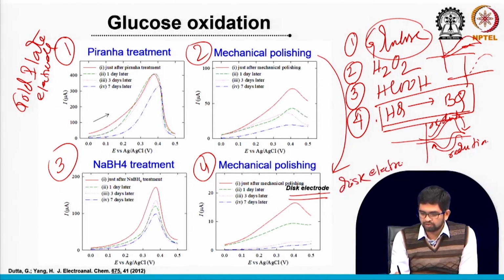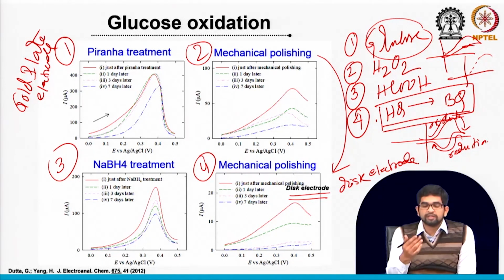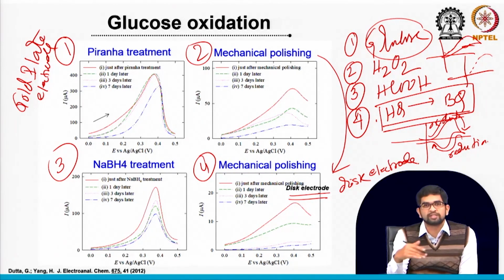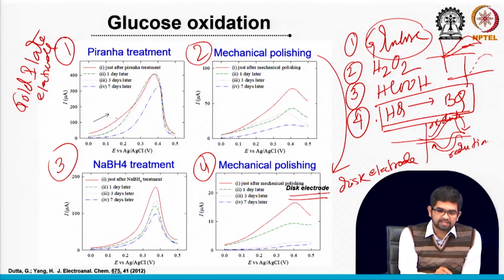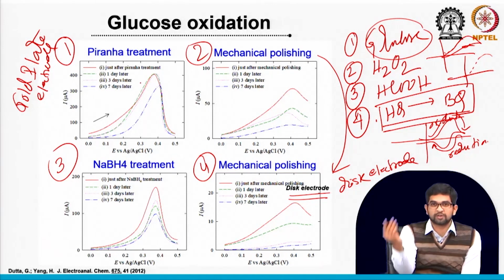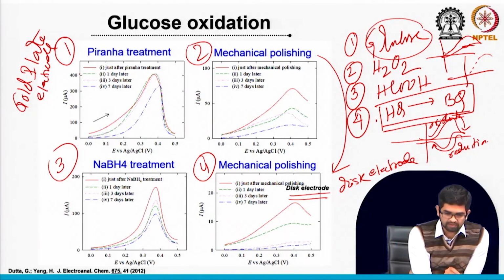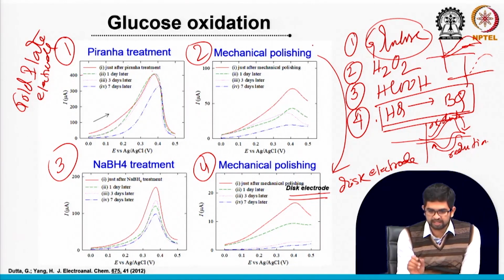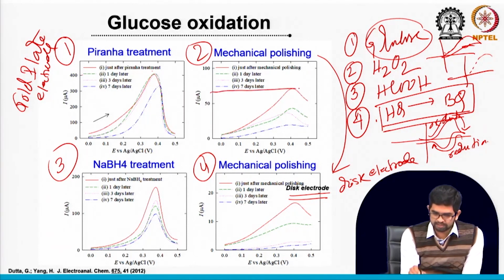So why do we change from plate to disc? Because when you develop a chip, mainly we are coating the electrode with some gold, right? We are not using pure gold. So we wanted to see all the treatment effects on the coated gold and on just pure gold. In the first 3 cases, the coated gold, you can see the piranha treatment case. Just after treatment, we generally get huge electrocatalytic activity. If you compare the others, it is around 400 microamps. But in the other case, mechanical polishing, it is too low, just this much. And for the sodium borohydride treatment case, it is up to here, around 80.